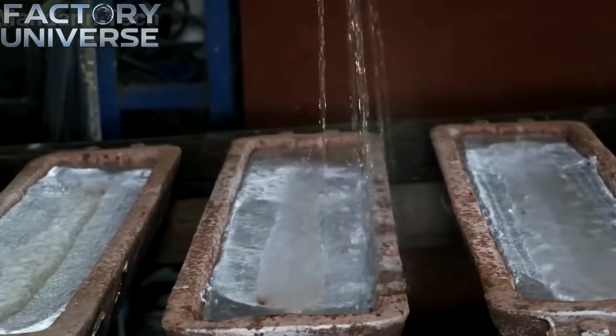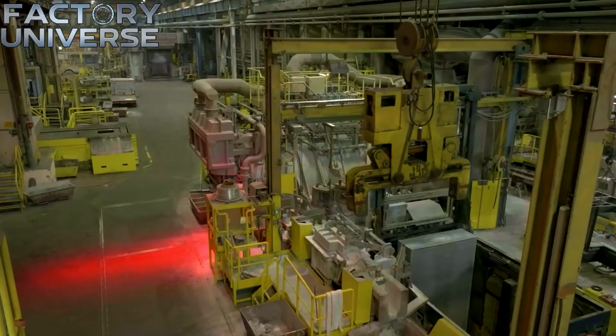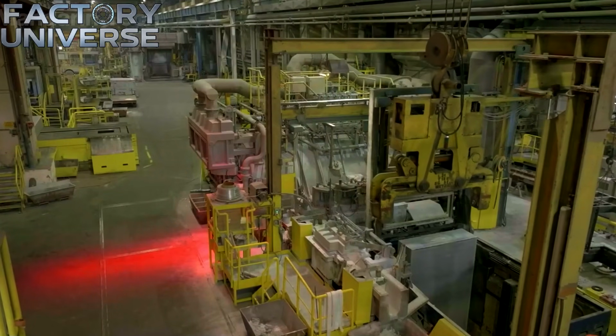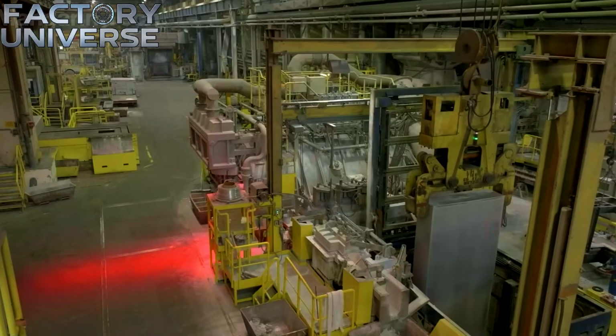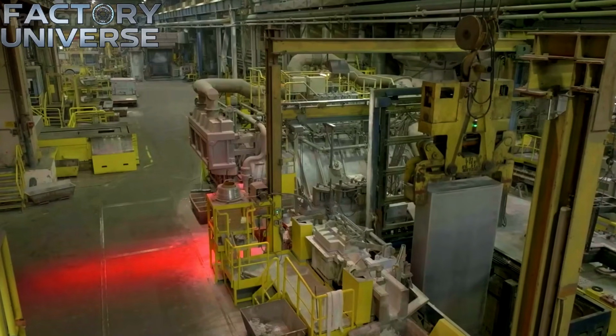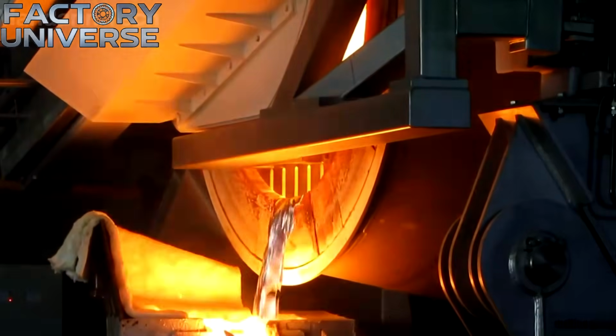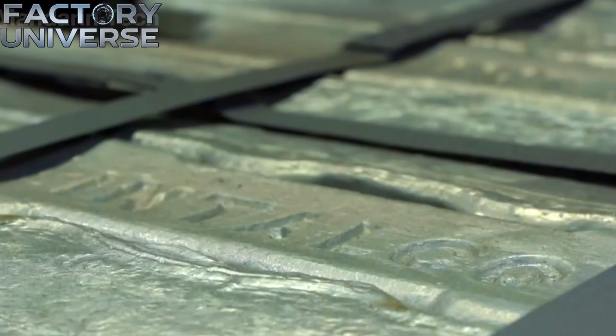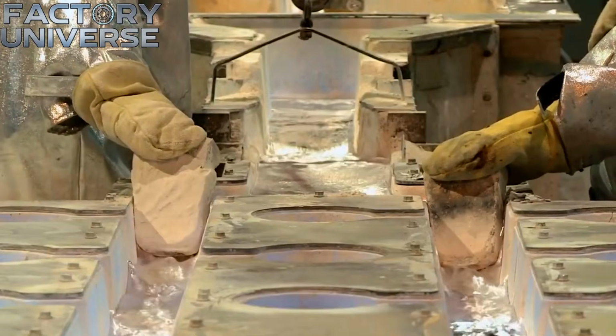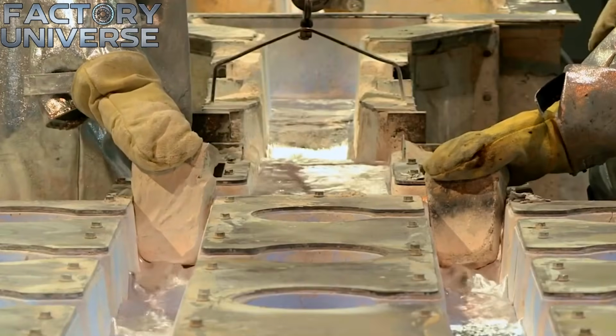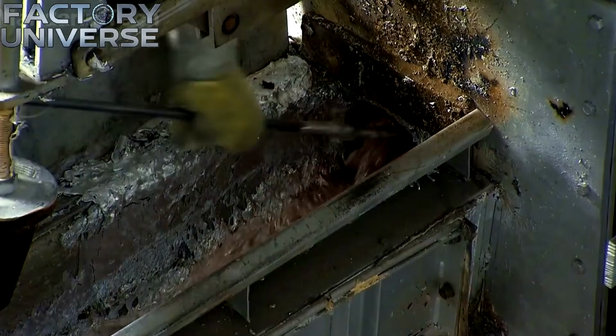control systems. If the metal flows at a rate exceeding the calculated limit, gas pockets or surface cracks can form immediately. If the mold temperature drops too low, solidification occurs unevenly, creating internal defects deep within the structure. Every variable must remain in perfect balance. The process is only gaining momentum.